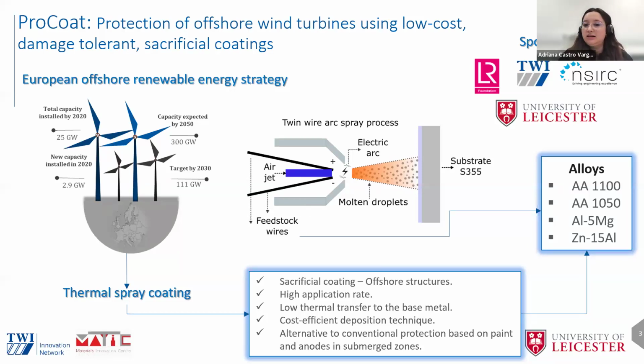So in that sense, the material in molten or semi-molten phase is accelerated onto the substrate by a gas stream system. So we obtain a coating thickness onto usually S355, which is a carbon steel, quite common in offshore applications. So here on the right, you can see the different materials that we can have as consumable, especially aluminum alloys. In my presentation, I'm going to focus on the alloy 1050, which is ideal for immersed zones.